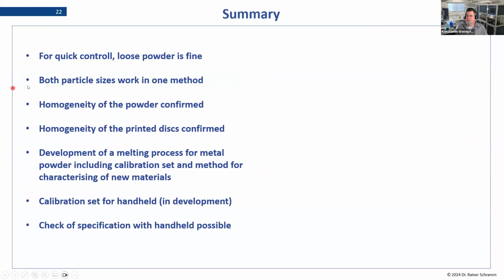The particle size in the powder does not really play a huge effect from what we saw in our tests here, which is a surprise because that's quite unusual for XRF. But in this analytical circumstance, and because it's a very homogeneous powder, the particle size effects are not really observable. Let's say they don't really play a role. We can ignore them, and we can use the same application for both of these powders, the one for the laser beam and the one for the electron beam, even though they have different particle sizes.